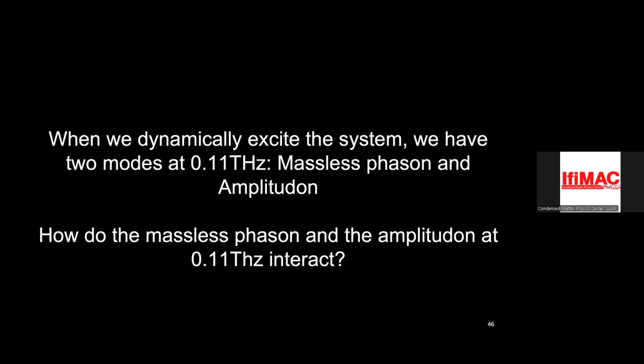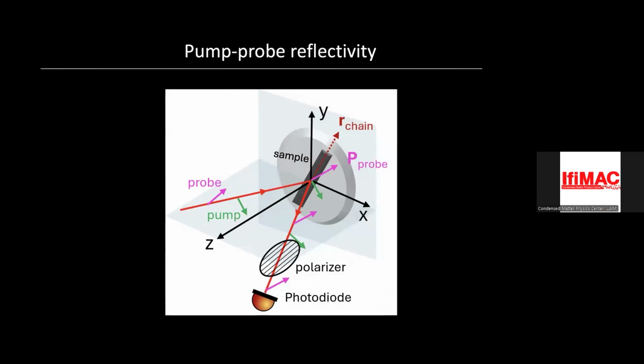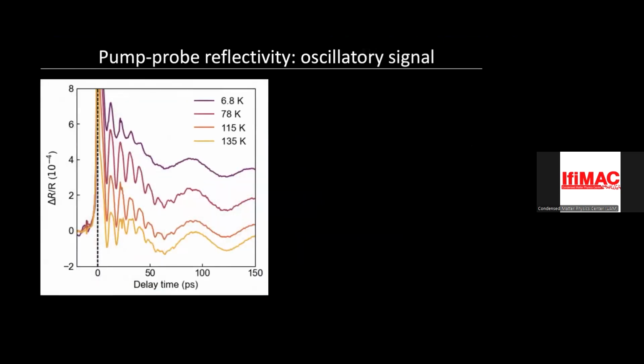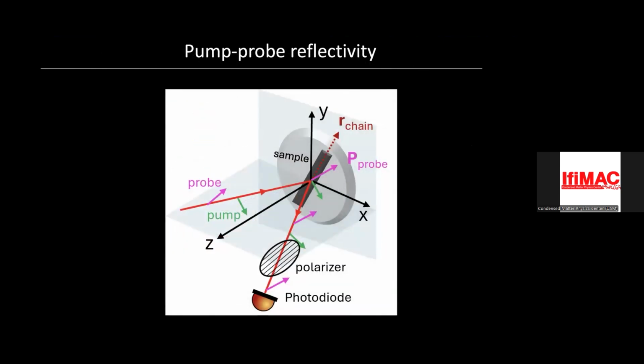This is like a dynamically excited system. You have these dynamic excitations. Do these things interact with one another? And to answer that question, in the same SCM, we have another technique, which is pump-probe reflectivity. They're called the pump and the probe here because they actually are the pump and the probe. The pump excites the sample, and then we measure the reflectivity of the probe.